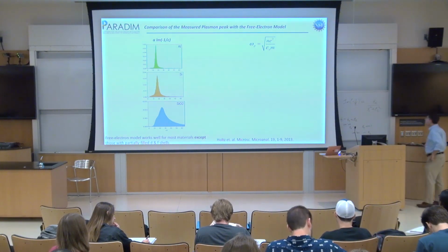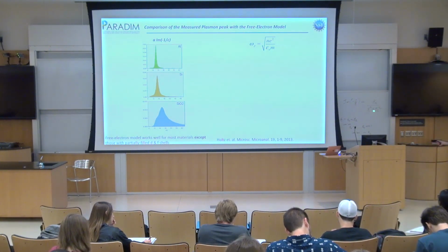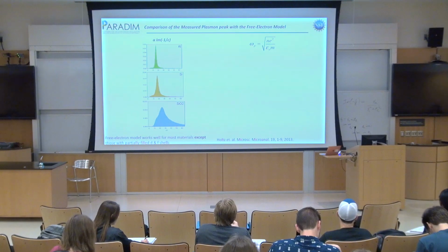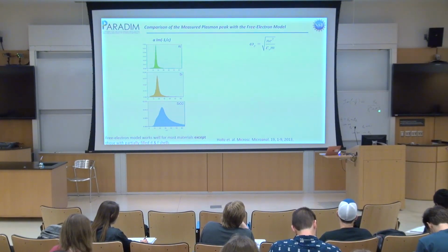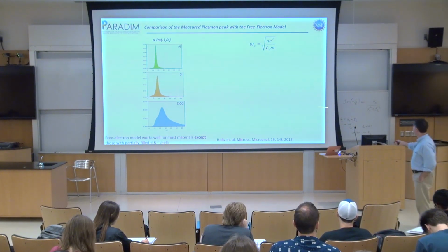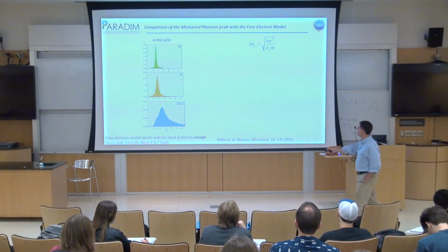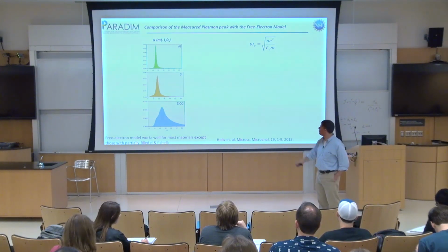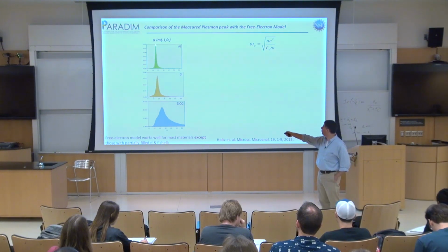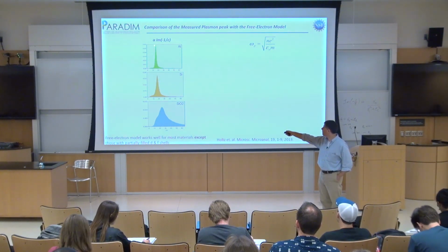The tricky thing that happens is when epsilon 1 and epsilon 2 are large, then this function has funny shapes. The plasma frequency is the point at which epsilon 1 hits a pole. This whole thing blows up as a denominator, and then you get these lovely sharp peaks. So aluminum, which is a free electron gas, has a beautifully sharp peak at the plasma frequency, and it's nice